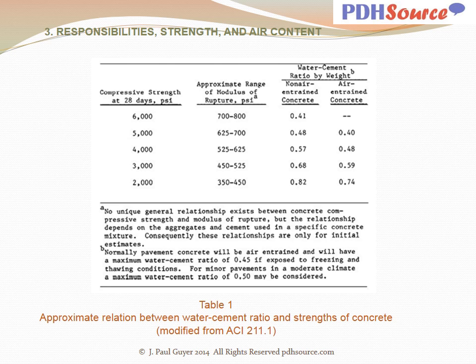Table 1 provides a picture of the approximate relationship between water-cement ratio and strengths of concrete, modified from ACI 211.1. Compressive strength, as an example, at 28 days, 6,000 psi. Approximate range of modulus of rupture, psi 700 to 800, on up to compressive strength at 28 days of 2000 psi, approximate range of modulus of rupture 350 to 450, and the water cement ratios as for an air entrained and non-air entrained concrete indicated in the last two columns.